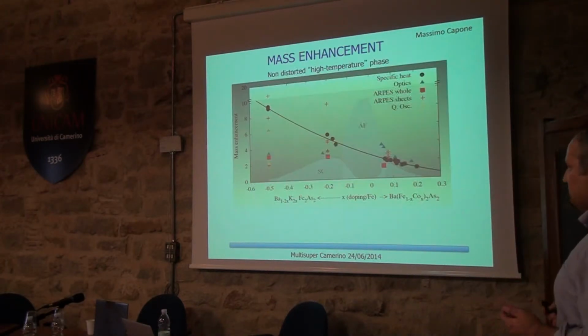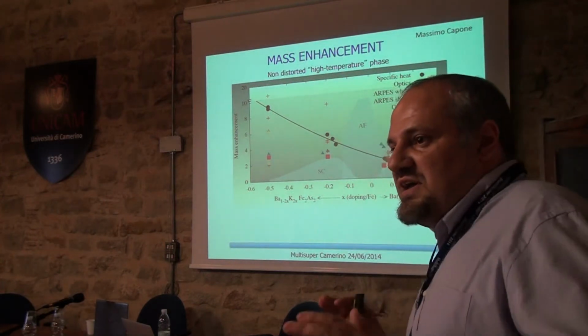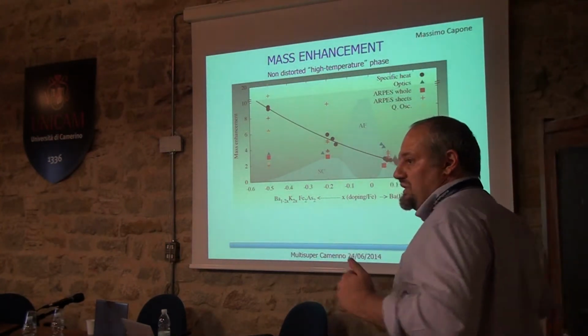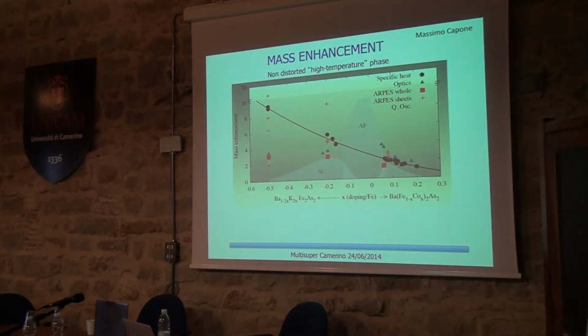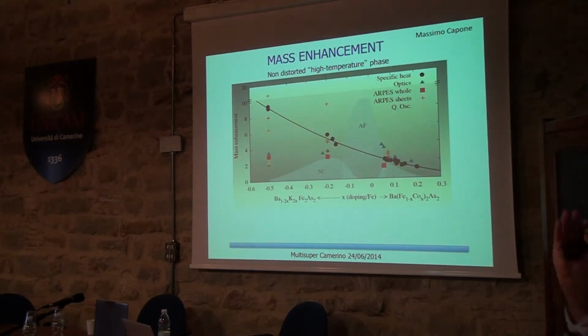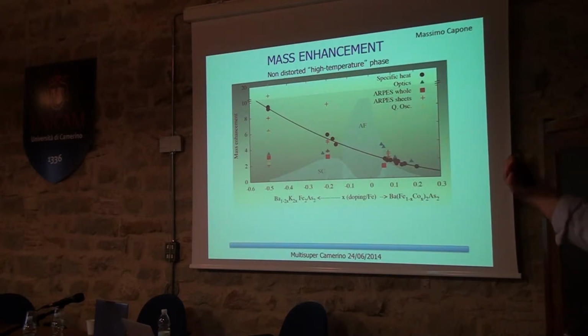So now let's go back to our materials, and go back to the experiments to see if there is something at least reasonable in what I'm saying. Here, I will show you some collections of effective mass enhancement from experiments. This is done for the 122 family, which is the one which can be doped either with electrons, replacing iron with cobalt, or with holes, replacing barium with potassium. So I'm putting everything on the same slide. Around here there is the antiferromagnetic spin density wave, and then there are 2 domes of superconductivity, but I'm just referring to measurements above the ordering temperatures and estimates for the effective mass.